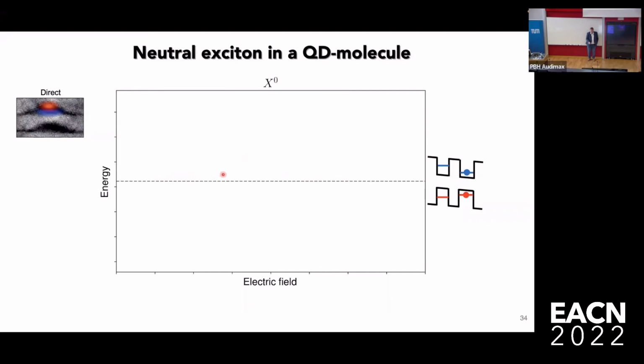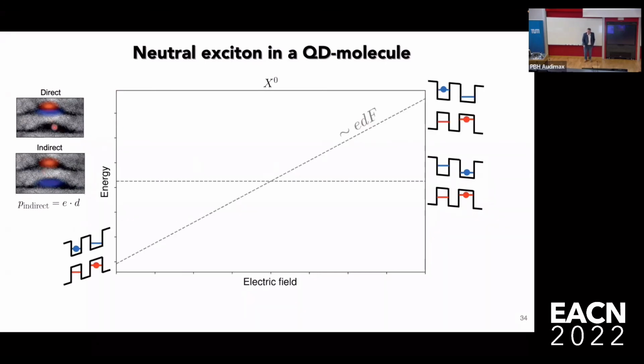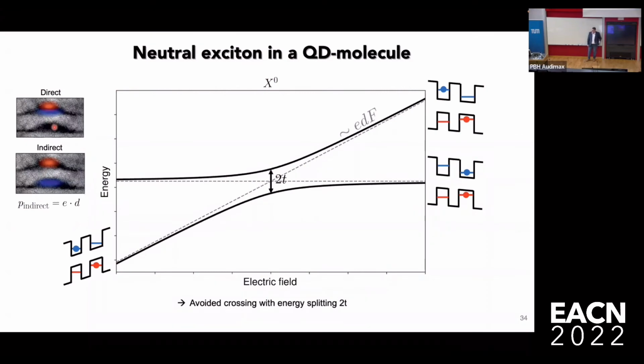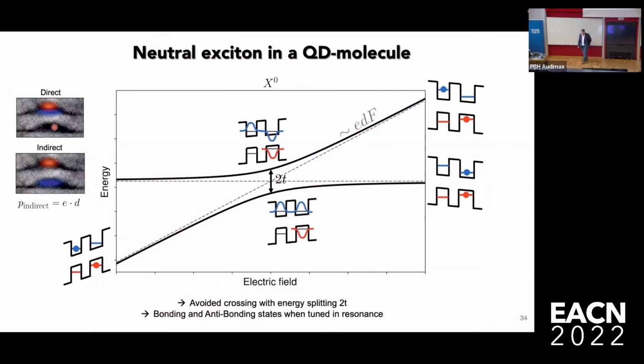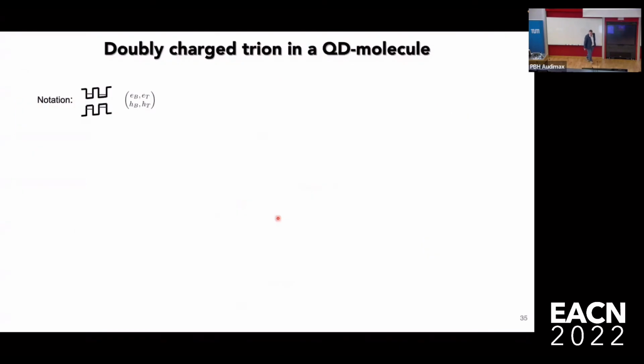It doesn't Stark shift very much as a function of the electric field because it has very little permanent dipole moment. At the same time, if you move one of the 2 particles into the other quantum dot to make an indirect exciton, this has a significant dipole moment. And because of that, when you vary the electric field, it should shift very strongly via the DC Stark effect. And of course, where they come onto resonance, if there's coherent coupling between these 2 states, they should anticross. The splitting then is dependent on the strength of the coupling. And that produces then hybridized states where the orbital states form, let's say, antisymmetric and symmetric combinations. So here I'm showing you for the electron hybridizing between the 2 quantum dots.